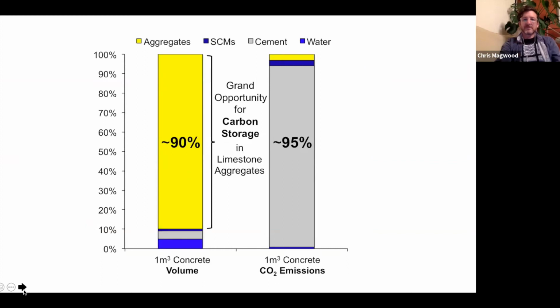So this is a graph that is showing a volumetric cubic meter of concrete, and aggregates, sand and coarse aggregate account for 90% of the volume. Portland cement accounts for very little, anywhere from 5 to 10% of the volume. But if we look at the CO2 emissions associated with each of those constituents, Portland cement production accounts for 95% of the CO2 emissions.